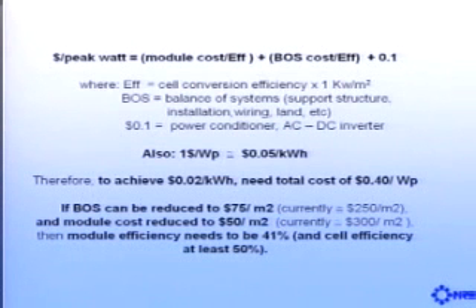Now, the point I'd like to make is that there's a lot of effort on reducing the cost, but this is not enough, because if you do want to get to 1 to 2 cents per kilowatt hour, you can show, using that equation up here, that if you could reduce the balance of systems to $75, it's currently this number, and if you reduce the module to $50, it's this number, so these are major reductions in cost, you would need the module efficiency to be about 40% and the cell efficiency, since you lose some in the module, say about 50%.